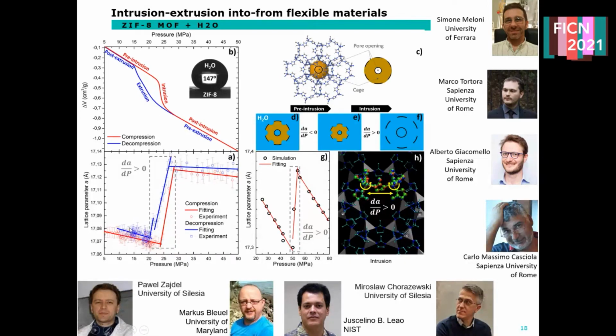But looking into the structural behavior of the system during the intrusion-extrusion cycle, which was obtained using in situ neutron scattering, one can see that the lattice parameter, or the unit cell in this case, of the material actually behaves very peculiarly during the intrusion process, particularly during the intrusion of water. There is a very pronounced expansion of the unit cell. We can see this from the experiments, which were obtained in collaboration with the authors, shown at the bottom of the slide, and we can also see this from MD simulations obtained from the group you can see on the right.